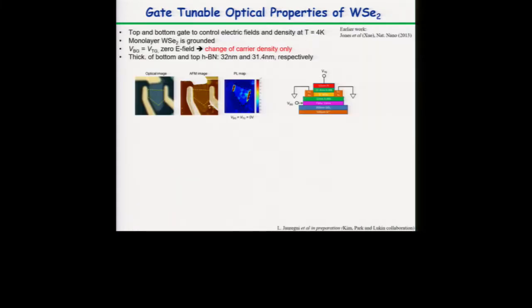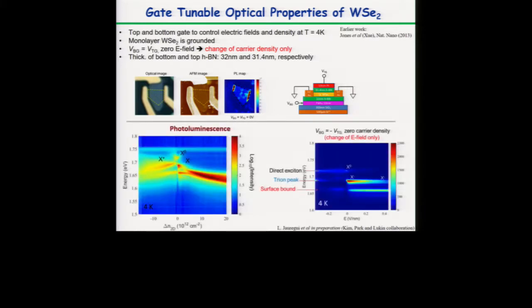Okay, so we also can now look at the electro-optical properties of a single layer. So we have now placed this tungsten diselenide in between boron nitride. This is a heterostructure of boron nitride. We have top and bottom gates. We can control the amount of carriers in the channel. As I mentioned, we can have a reasonably good contact on them. And we can look at the photoluminescence and how photoluminescence changes with change of carrier density or change of electric field, since we have two gates on top and bottom.